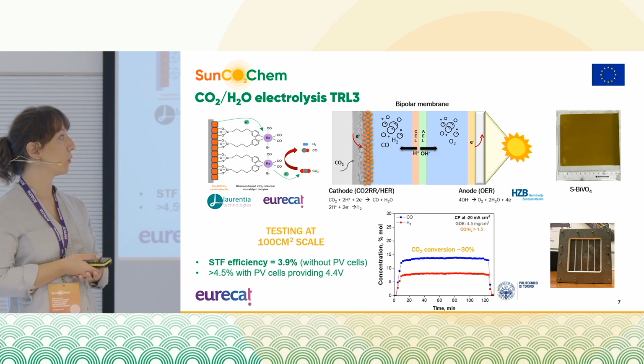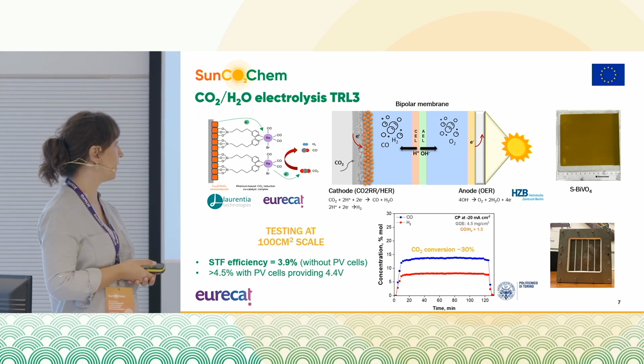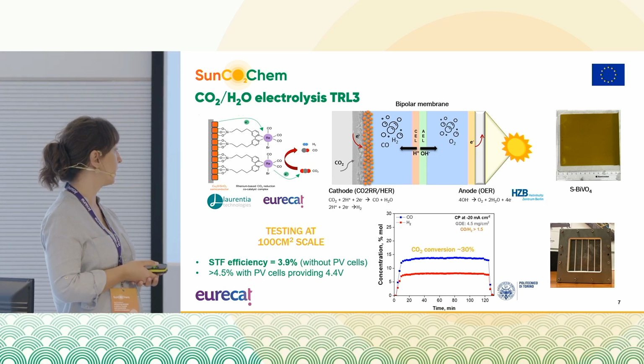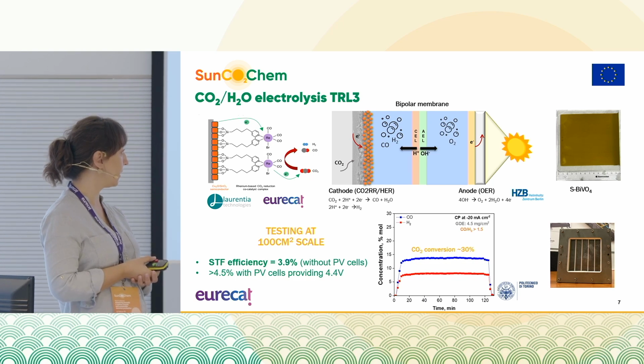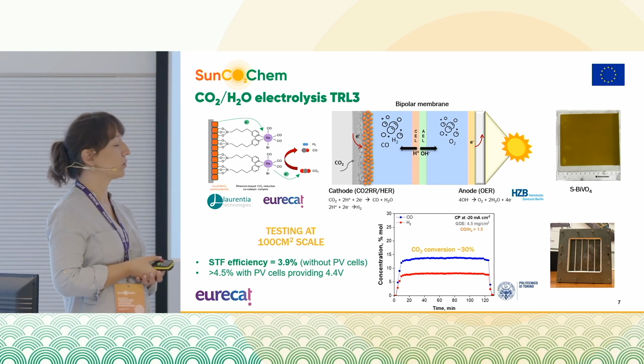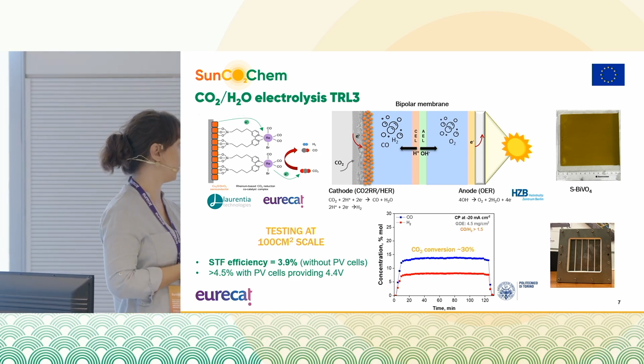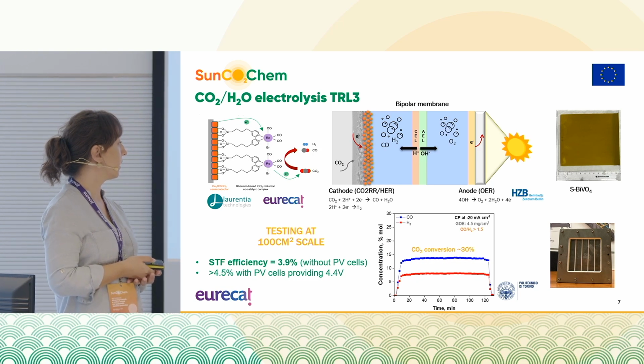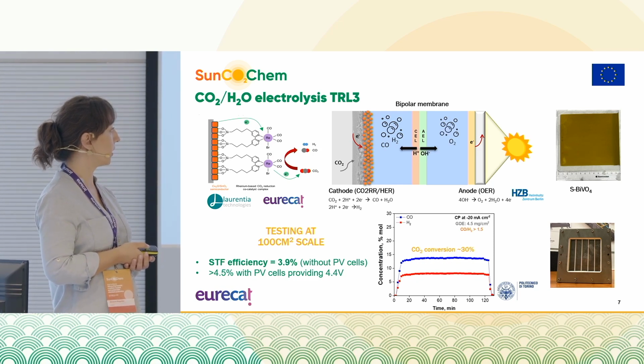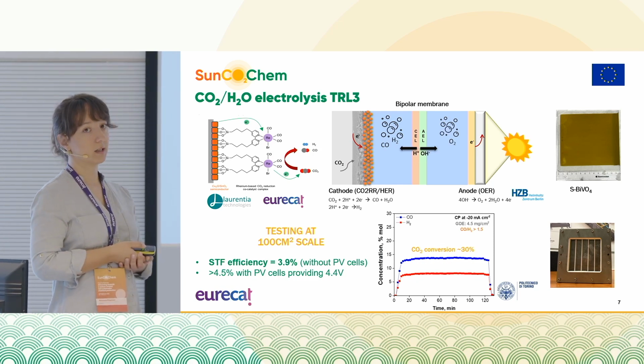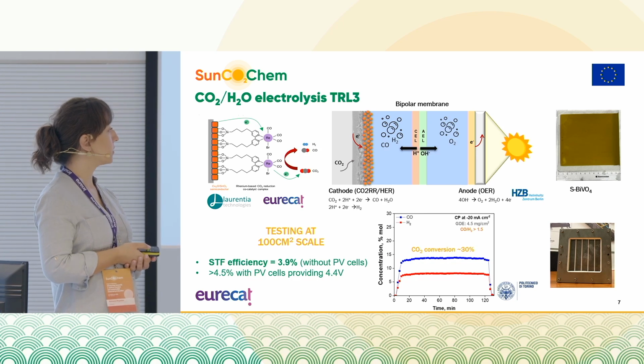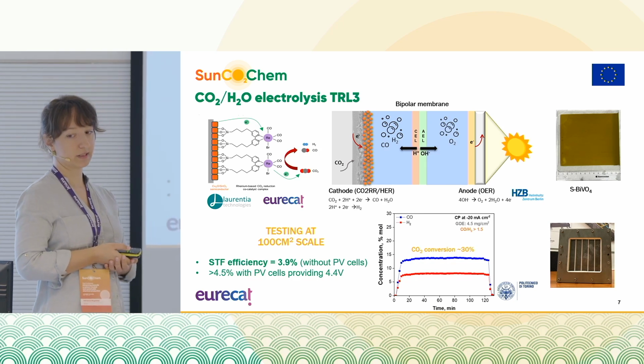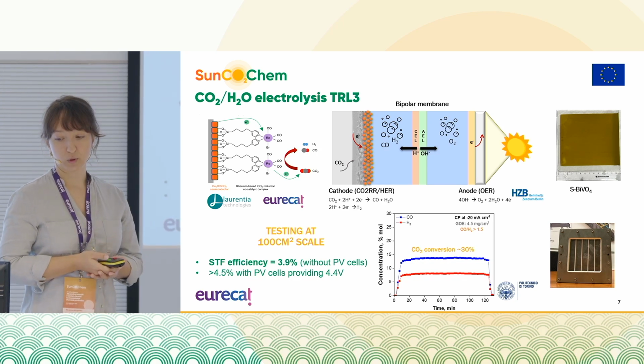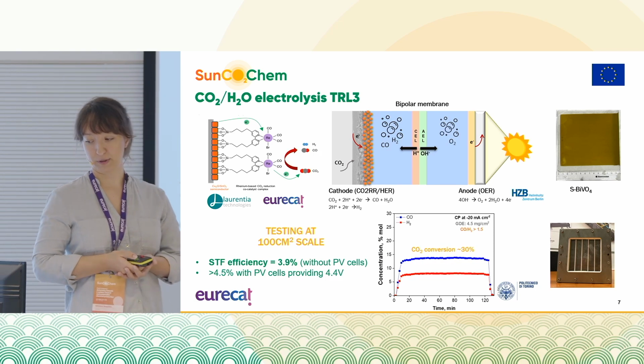This system was tested at the TRL3 level at a single cell scale with 100 square centimeters of active area. And during the 2 hours of operation, we were able to obtain a stable syngas production with a CO2 conversion of around 30% and sun-to-fuel efficiency of around 4%.